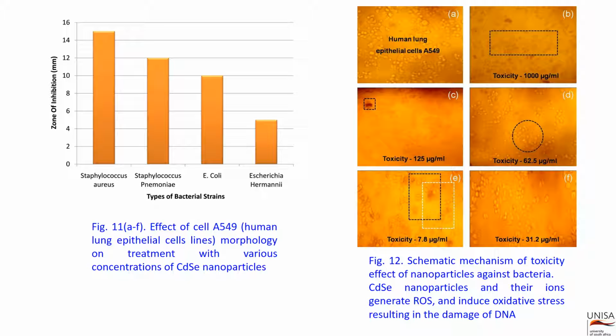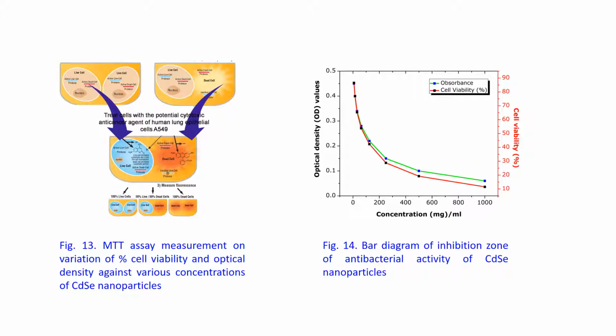Therefore, the percentage cell viability was calculated using this formula, which means the percentage cell viability equals A570 of treated cells divided by A570 of control cells times 100. The cell control and the sample control are included in each assay to compare the full cell viability measurements. In the investigation, different concentrations of the cadmium selenide nanoparticle were treated with a known quantity of cells and the percentage viability for each dose value was measured using the MTT assay, as shown in figure 13 also. After exposure of the cadmium selenide, a dose-dependent significant decrease in cell viability by the MTT test was observed.